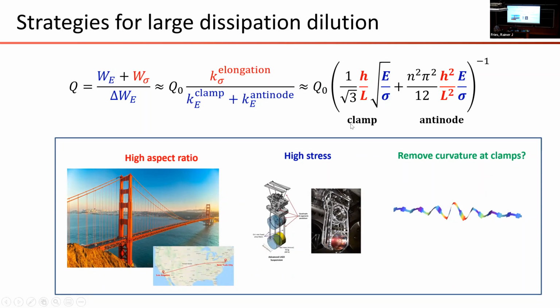So if you want a high dissipation dilution, you need to have very high aspect ratio, you need to have high stress, and it also would be helpful to get rid of the curvature at the clamps, which motivates looking for techniques to so-called soft clamp the mechanical oscillator so it doesn't have that extra curvature. In fact, if you could do that, then the dissipation would go from the aspect ratio to the aspect ratio squared. So there's a big win to somehow phononically engineering out the curvature of the clamps, which is something that's eminently doable using lithographic patterning techniques.